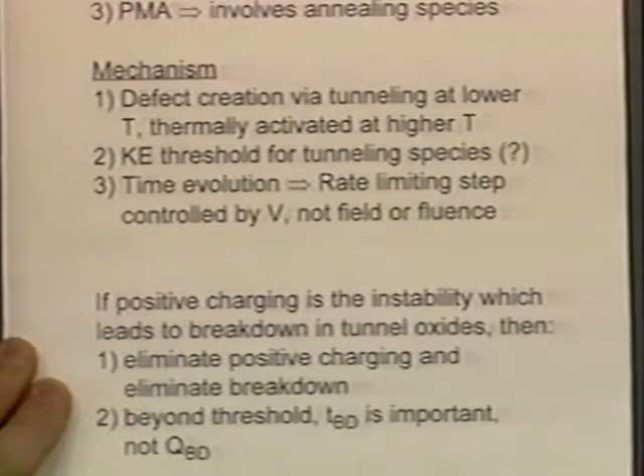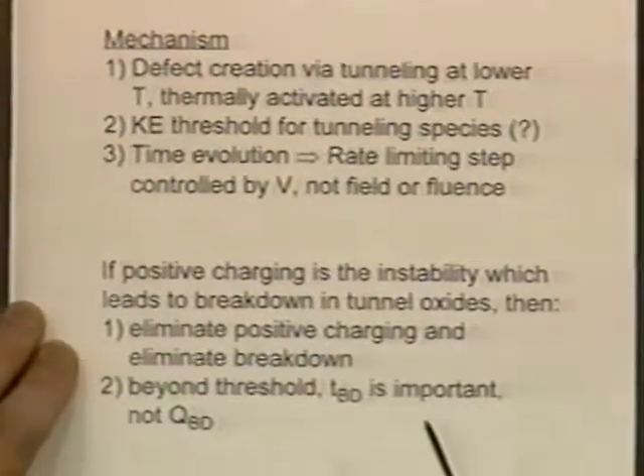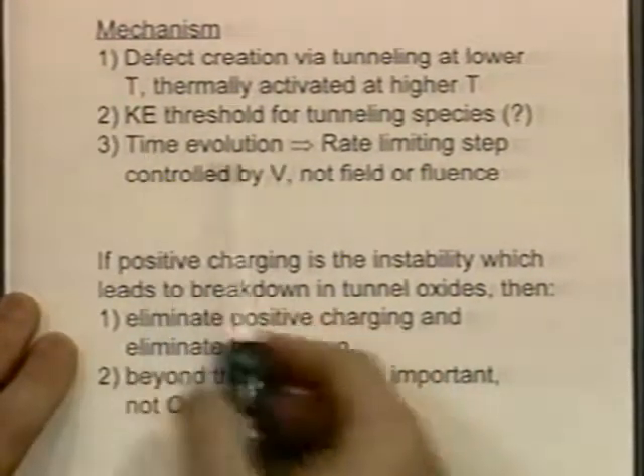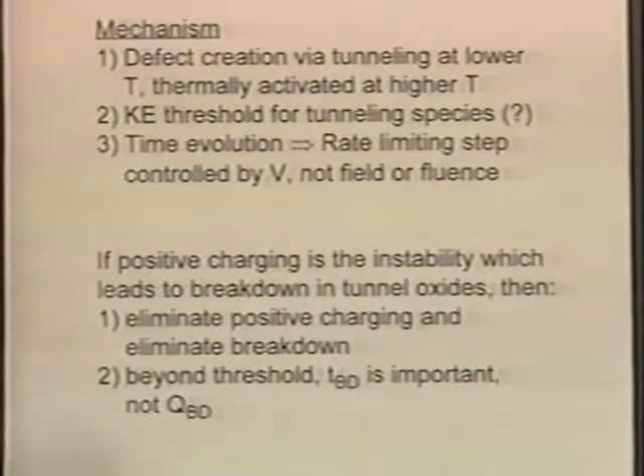I don't necessarily believe anymore that a kinetic energy threshold is involved. I don't even know if you need these tunneling electrons per se, at least for the direct creation of the defect. Instead, there's some time evolution process, and that's what this defect creation is, where the rate limiting step is controlled by the voltage and not the fluence.